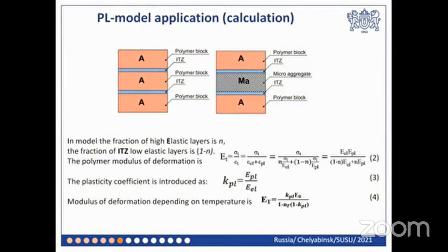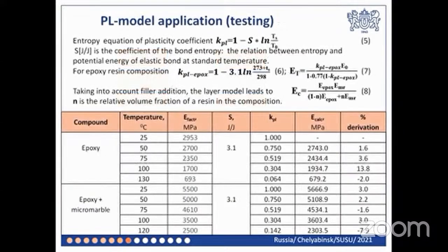Here is presented the calculation layer PL model. The viscoelasticity is modeled as packs of elastic polymer sheets stretched under load, with low rigid bonds between them. Here is presented the layer model with entropy factor for elasticity models under definite temperature. Final equations were received for epoxy filled by micromarble and others. The table presents the correlation of the entropy layer PL model: calculated and actual results differ by not more than 15%.